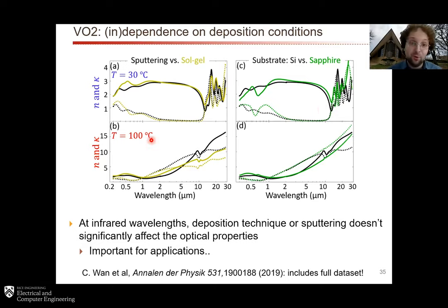And that's because you're far away from the interband transitions and you're far away from the vibrational transitions. And so not only do you have a region in the insulating state where the material is quite low loss, which is potentially useful for some applications, but also pretty much every VO2 film that you deposit is going to behave very similarly as far as its optical properties. We even deposited one film where you couldn't see an electrical transition at all because the film was so cracked and had so many voids, but the optical transition was almost exactly the same.